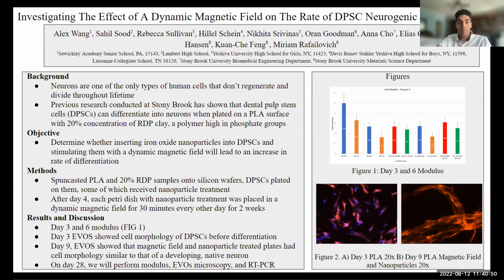Now, for our methods, we accomplished this by spin casting 24 silicon wafers with either pure PLA or PLA with 20% RDP at 2,500 RPM for 30 seconds. That helped us create thin polymer films, and pure PLA was just our control. And then we plated the DPSCs onto the surfaces using an initial seeding density of 1.5 times 10 to the 5. And after, some of the samples received nanoparticles and some of them didn't.